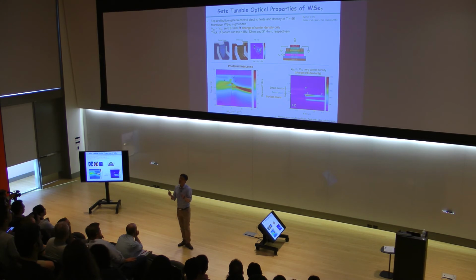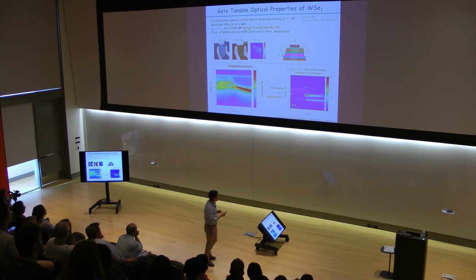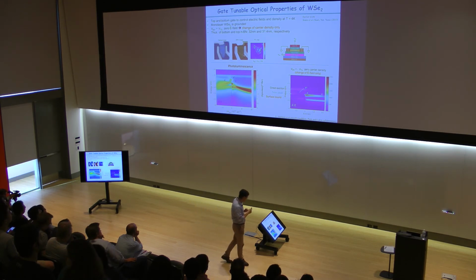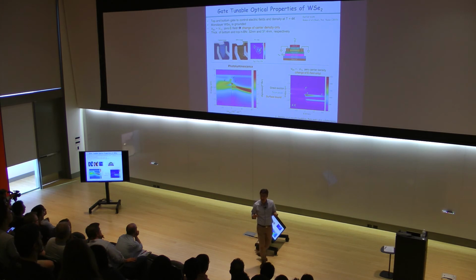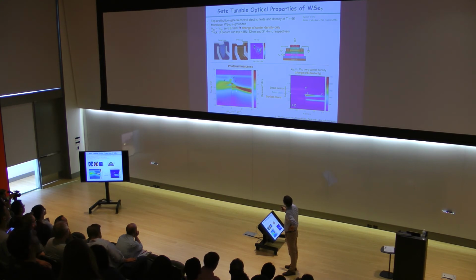If we apply the same polarity of voltage onto the gates, we can change the density without applying an electric field. Or if we apply different polarities on the top and bottom gates, we can change the electric field without changing the density. And what you see here is the spectrum. The bright red is a peak, and blue is a dip.